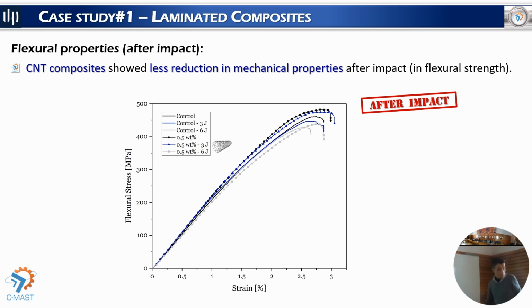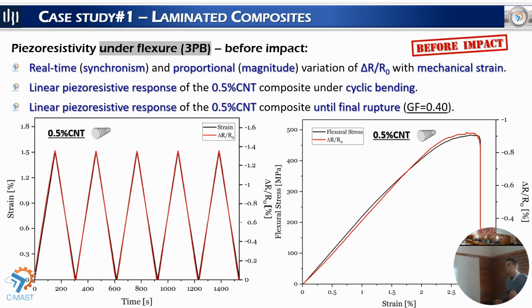Okay, now let's move to the electromechanical properties, which are, I would say, the main results that I want to show you here. We start by studying the piezoresistivity of these laminated composites under flexural experiments by 3-point bending tests. In this graph, the black line corresponds to the mechanical signal, the mechanical deformation, and the red line is the electrical resistance variation. And we see an overlap of both signals during the 5 cycles of the experiment.